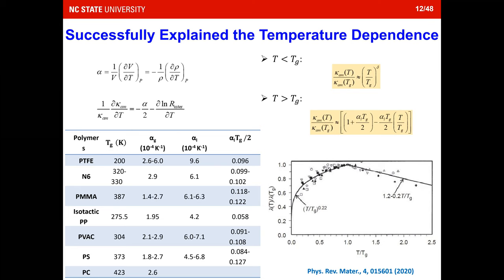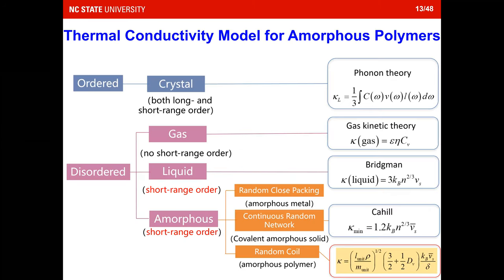So we also use the simple thermal resistance network model, which explained well the temperature dependence for amorphous polymers. So we think we can add this equation to this big picture of the thermal model. And when we add them together, immediately we found there are a lot of common things, and some differences. If you look at the equations for liquid, for amorphous solid, and our recently derived one for amorphous polymer, they all have the kB and vs. vs is the speed of sound, but they also have some difference in terms of the exponents in the end, which is the kind of atomic density, right?